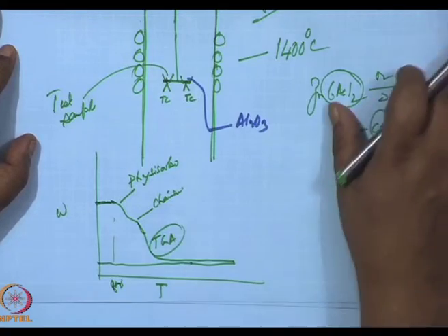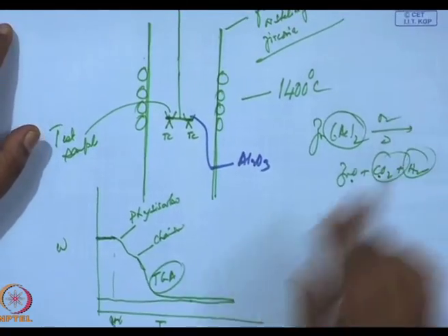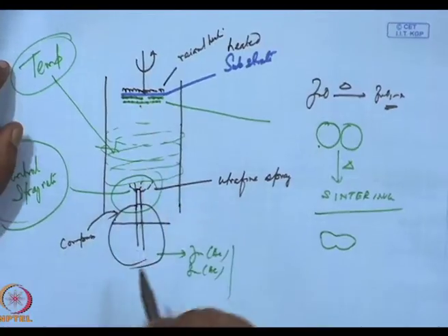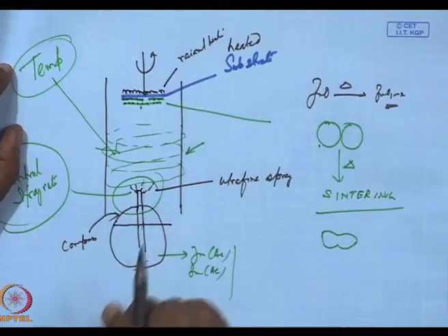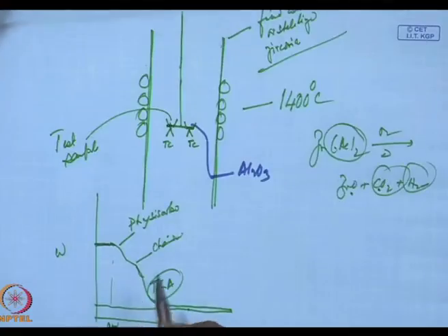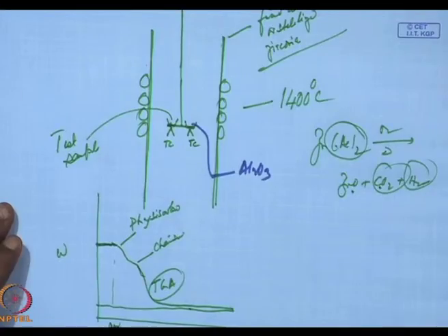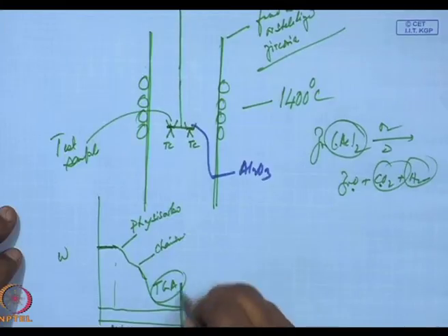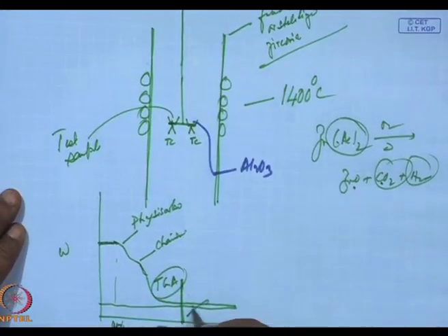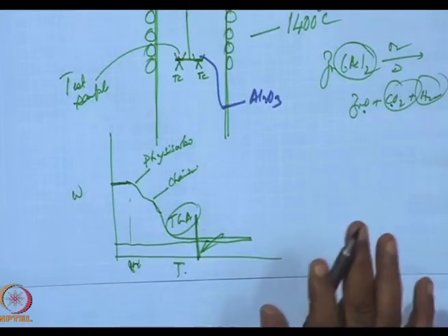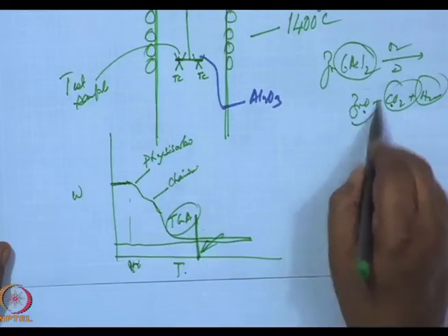Now, what does this tell us? When I am going to deposit zinc oxide over here, by spraying a zinc acetate, I want to know what should be the preferable temperature of the coil. So this TGA has told me that the temperature should be somewhere over here, because at this temperature all the zinc acetate has decomposed, giving me a zinc oxide.